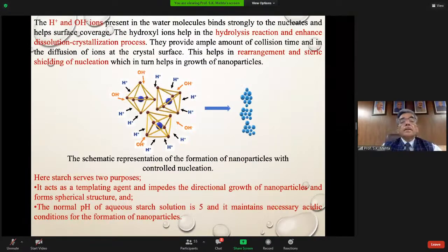Basically, the hydrogen ions and hydroxyl ions present in the water molecules bind strongly to the nucleates and help surface coverage. And the hydroxyl ions help in the hydrolysis reaction and dissolution crystallization process. They provide ample collision time, as you can see in the picture, and the rearrangement and steric shielding of nucleation, which in turn helps in the growth of nanoparticles. So good nanoparticles can be produced.